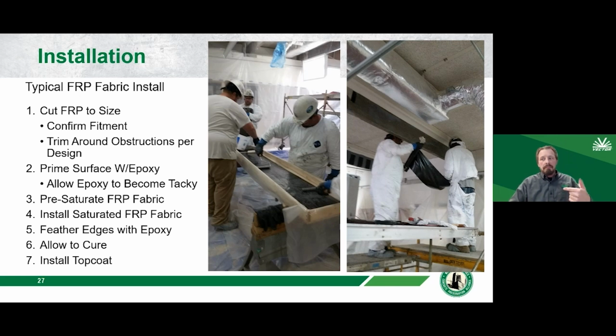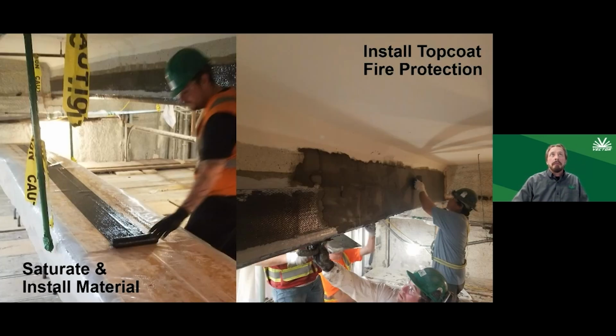We do have layup machines that we can use as well. So you can do this by hand, or with the machines. We use those on very, very large projects to saturate that fabric. Once it's fully saturated, then we install it into place, work it over by hand, and allow it to cure. Once everything's cured out, then we can install a top coat.